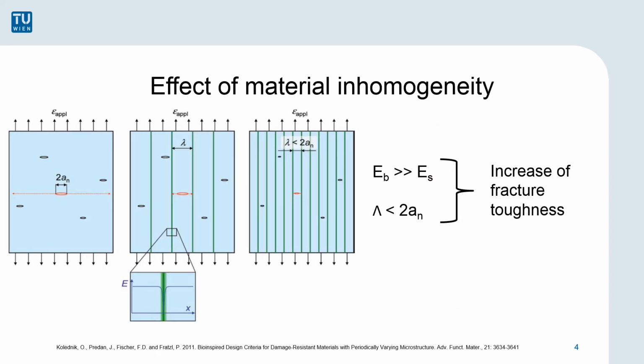We've seen before that the deep-sea sponge manages this impossible task to gain high load-bearing without being brittle like glass. The underlying effect is called the material inhomogeneity effect. The fracture toughness of a brittle bulk material can be drastically increased by the introduction of thin compliant material layers. For this effect to work, the mechanical properties of these materials have to differ substantially. The Young's modulus of the bulk material must be at least 5 times higher than the Young's modulus of the compliant material. On the left side, you can see a testing sample under tension from top and bottom.